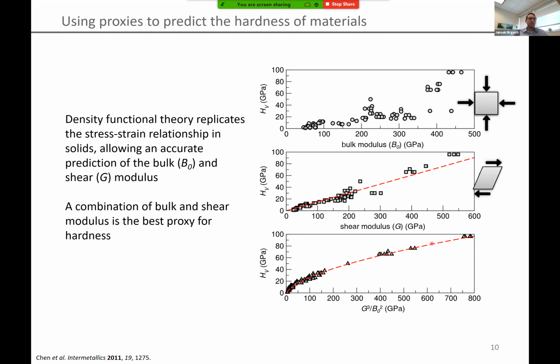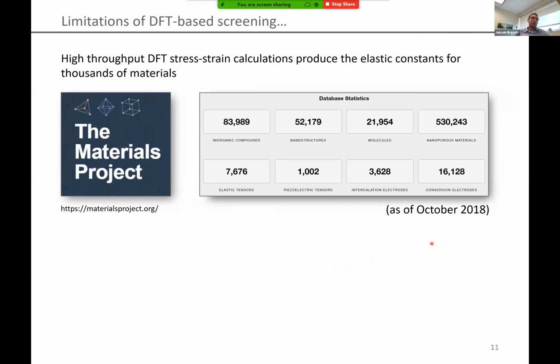Where we were really sort of intrigued is the fact that bulk modulus and shear modulus are both intrinsic materials properties. And better yet, you can actually calculate bulk modulus and shear modulus using first principles calculations. So fortunately for us, right around this time is when the Materials Project started making their first push of elastic tensors.